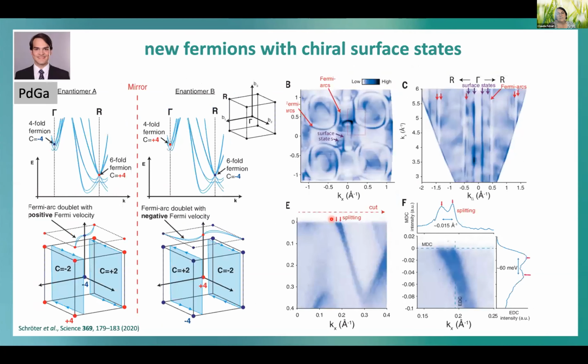But is there a better way to, okay, and then the second point, what we wanted to find out is, can we really see these large Chern numbers, which is larger than in simple Weyl semimetals, with the Chern number plus 4. And indeed we can do this if we go to compounds which have a large spin-orbit coupling. So you see then a splitting of the Fermi arc. So you see that every Fermi arc is 2 times degenerated, and this corresponds to the Chern number of 4.